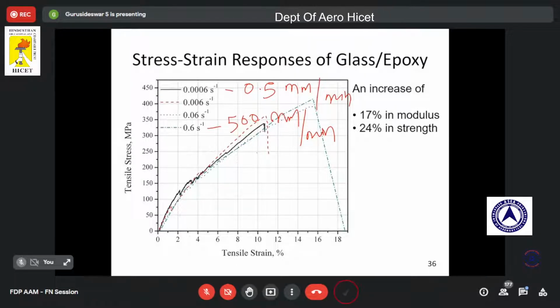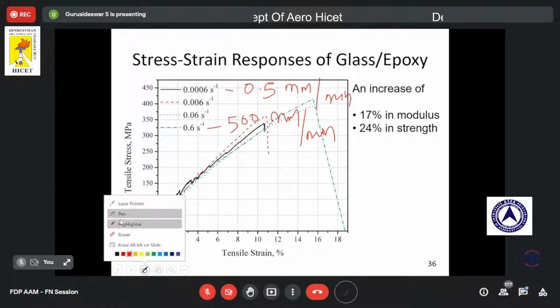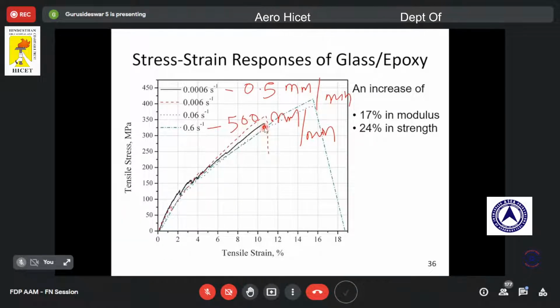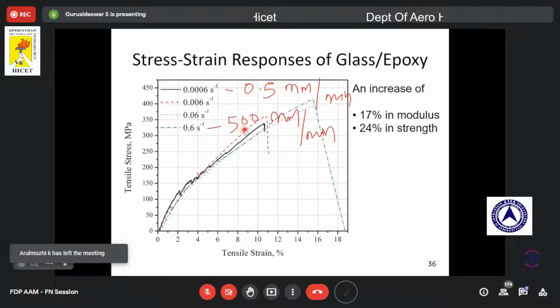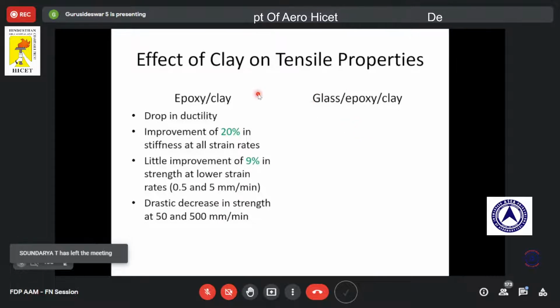Yeah. So here you can see the black shows the stress-strain curve of your glass epoxy at the lowest strain rate, 0.0006, 0.5 mm per minute, wherein this blue shows the stress-strain curve of glass epoxy at a higher strain rate, around 500 mm per minute. So you can see there is a drastic increase in the strength. This is what we observe from glass epoxy composites. So this is the effect of clay on tensile properties.